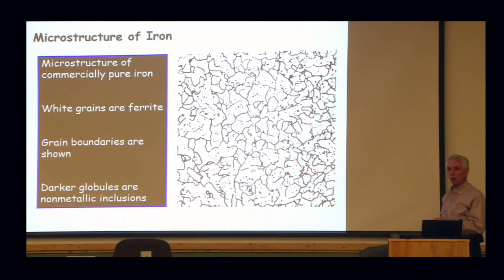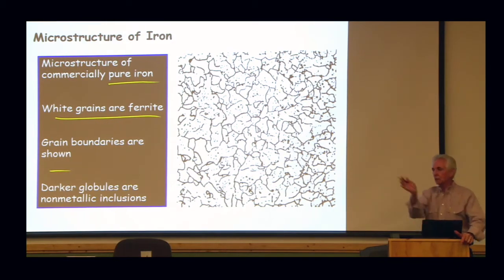Here is the microstructure of pure iron. The only thing I know that's pure iron is tie wire and those old cores that used to be in the welding machine. Everything else is steel, a little bit of iron in it, a little bit of carbon in the iron. So this is just pure iron. The white grains are ferrite iron, and the grain boundaries are the little black lines that swivel around in there, and the dark globules are little particles that came off the polishing and grinding rock. They polished that until it was mirror-bright. Literally, you could pick your teeth, pick stuff out of your eyeball. Then they poured a reagent or an acid on it, and they etched it, and then they washed it with clean water, and they shone bright lights on it and blew it up 1,500 to 2,000 times and took that picture.